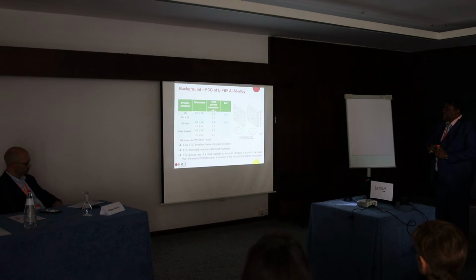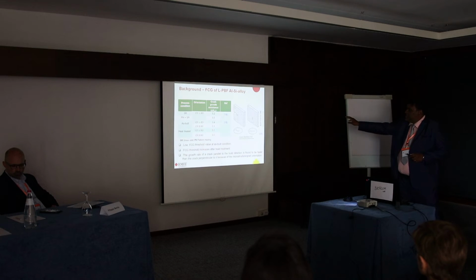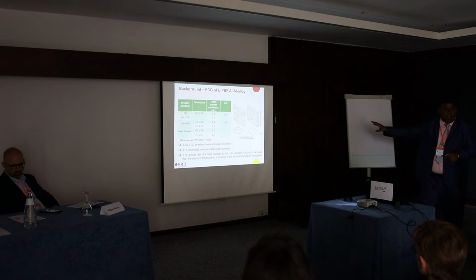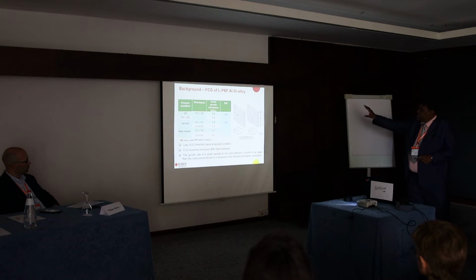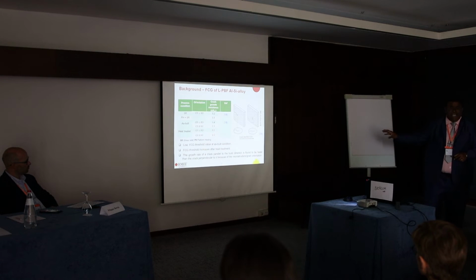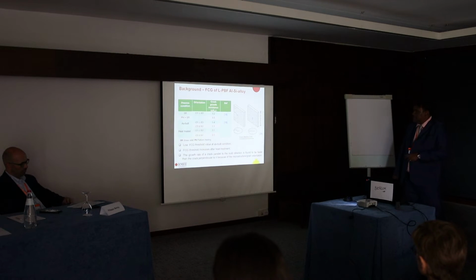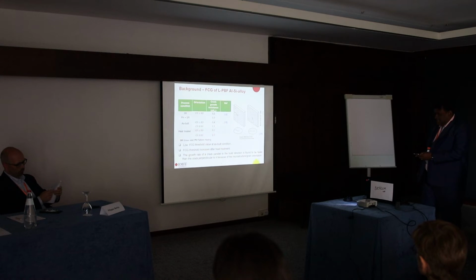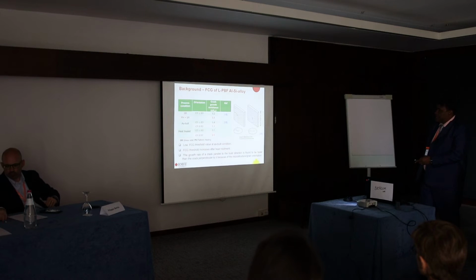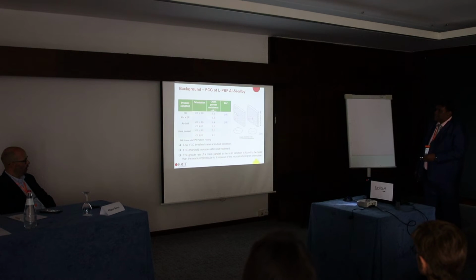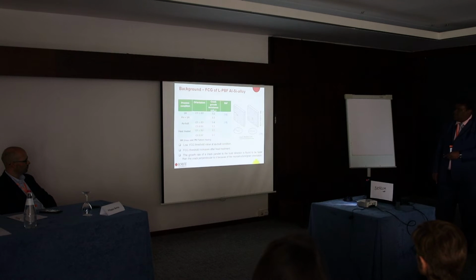what I want to highlight is this effect, what we already see in the literature. Depending on the build directions, we can get a change in delta K threshold, which is the crack growth resistance in the material. So as you can see with this red font, if we heat treat, both for cracks propagating perpendicular to the build direction and parallel to the build direction, we can get very high delta K threshold, which is the fatigue crack growth resistance, from AM material. So build direction is important, whereas as-built gives you really poor crack intensity threshold.